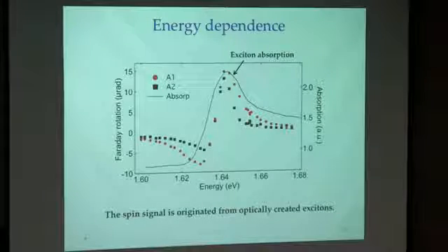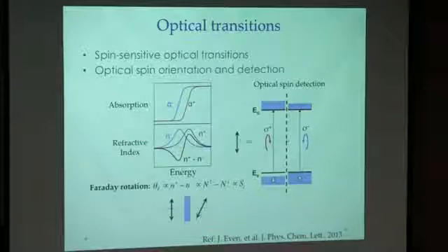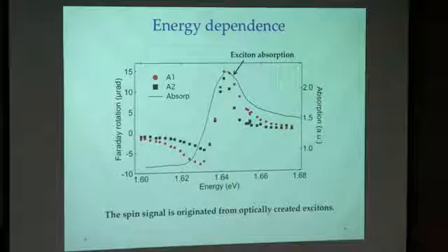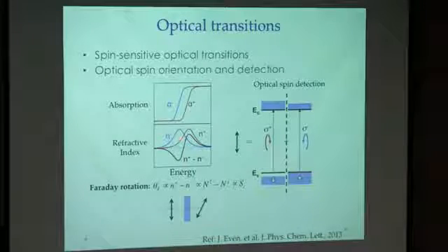That's an important piece of information. We experimentally verify that in our sample it has an excitonic origin. And by looking at the shape of this curve, I would like to remind you what we discussed about the energy dependence of the indices of refraction. We have exactly this shape. So everything we have measured so far demonstrates what you expect theoretically very well. It's like the best signal that you can get from simulation.